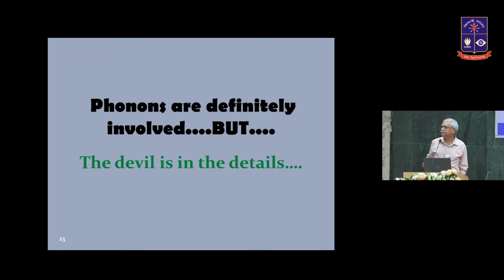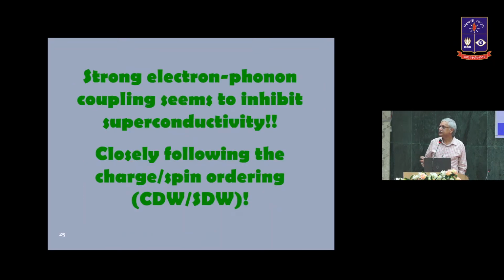So again, I'm summarizing. You can see here the electron phonon coupling constant is high. You are staying in this region, but the superconducting transition temperature is low. The oxygen vibration has a large effect on superconductivity. So naturally, you would expect the phonon is present, but superconductivity is in fact a bit suppressed where phonon is giving a large isotope shift. So what is the solution? And as I said, the strong electron phonon coupling seems to inhibit superconductivity.